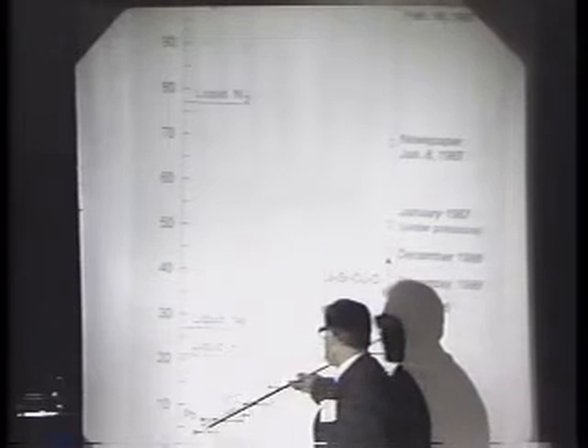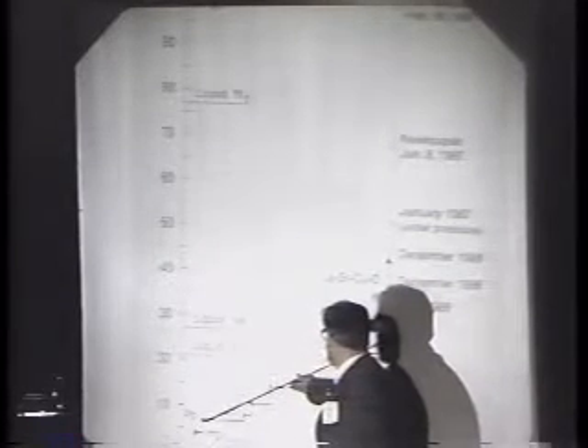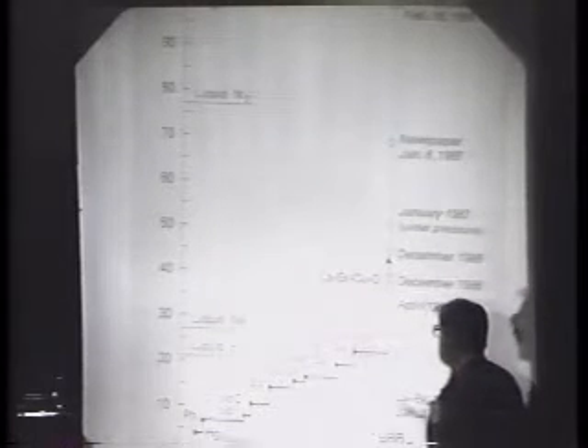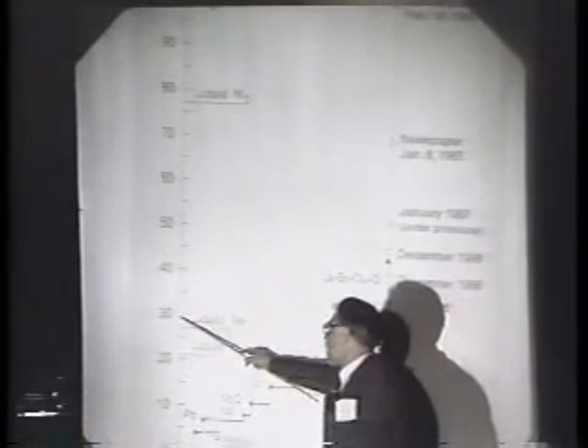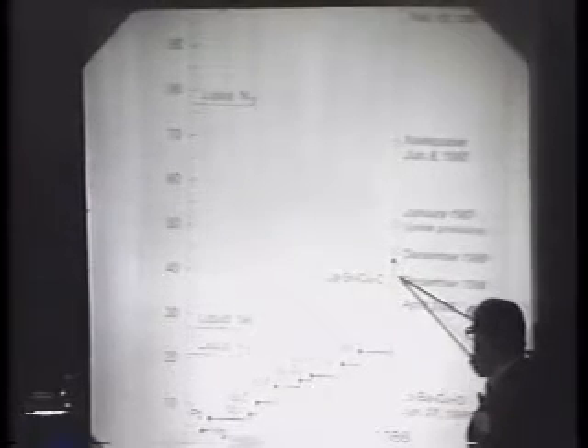I have plotted here transition temperature versus the years where they have been achieved, starting from the discovery in 1911. You can see from that graph that if you would extrapolate more or less linearly as a function of time, you would expect that by 1989 you would have reached about 30 degrees Kelvin. Instead of that, already by the end of last year, one had exceeded this extrapolation by quite a bit. And by now,